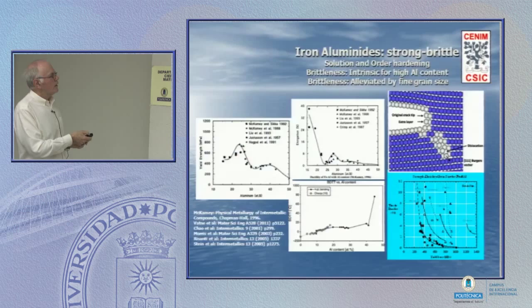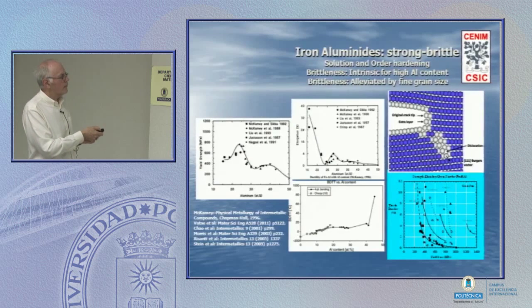Now, a summary of the properties. Here what we have is strength as a function of aluminium content. We're going from basically steel down here, which will be soft. As we add in aluminium up to Fe3Al, the strength increases dramatically. As I move from Fe3Al to FeAl, the strength comes down somewhat from this maximum, but is still respectably strong.